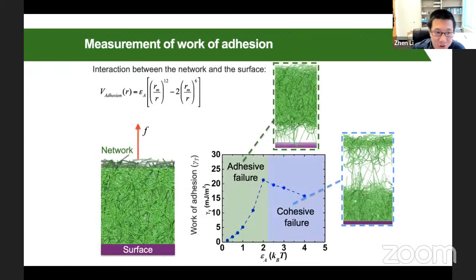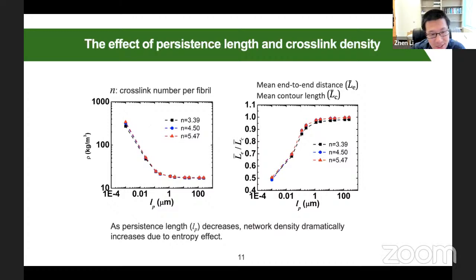Okay. Because if you have a shorter one and a longer one, and then you do the tensile test, you may have a longer curve for extension, because for example the short polymers may break at an early stage, but the long ones will not. That's true, I agree with you. This happens. If you look at the network of cellulose, the cellulose nanopaper, you can make it from shorter fiber or longer fiber, and you get a totally different stress-strain curve. That's just because of the difference in length.